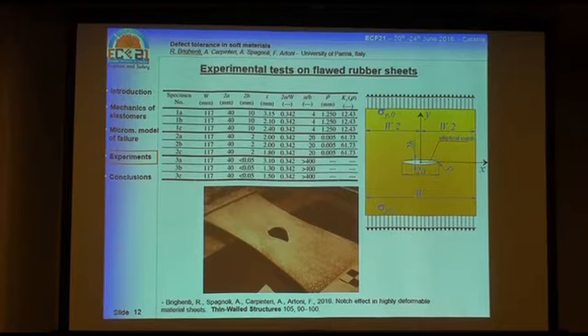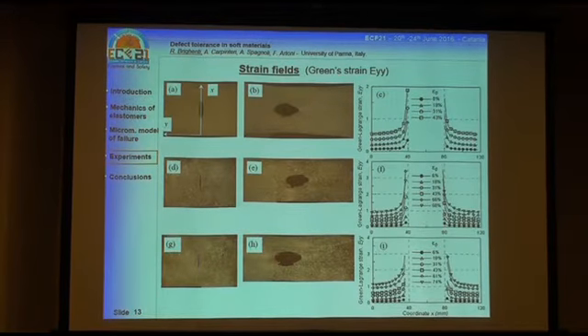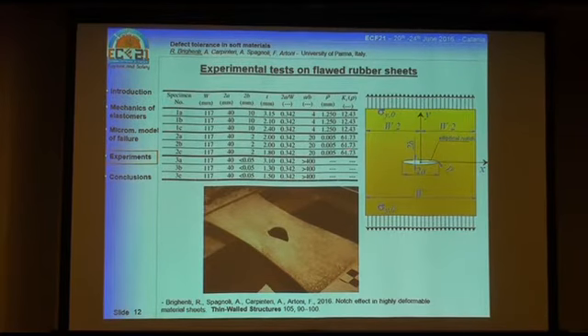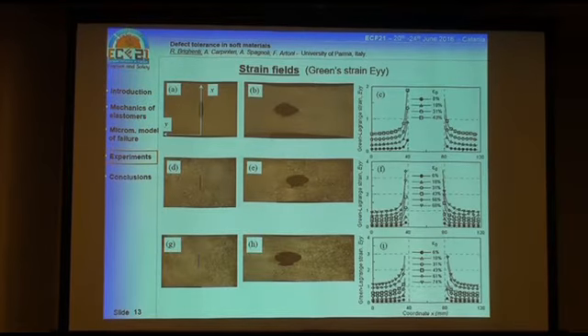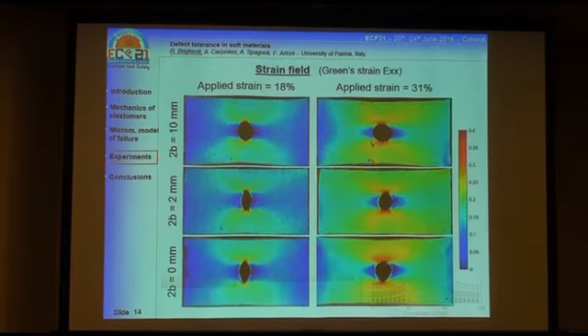And we try to determine the load displacement curve as well as the strain distribution inside the specimen by using digital image correlation techniques. So we measure precisely what is occurring in the material close to the notch tip. We have the case of the blunt notch, of the mild notch, and of the perfect crack, the straight crack here. And as you can observe, the deformation is very similar, irrespectively of the initial defect that is present in the structure. So we have from 12 to about 60 as a stress concentration factor for these two cases here, while we have the crack in this case.